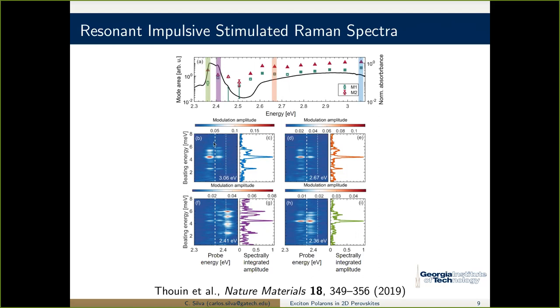So again, you saw this phase shift around exciton A. All of these normal modes, this Raman spectrum, is all centered around exciton A. You see exciton B, not much activity. We go to lower in energy, and we see basically the same thing. We're still injecting photocarriers, albeit with lower energy. But when we resonantly excite the two excitons, we see very different things. So we resonantly excite exciton A. Now we're pumping into exciton A and probing around exciton A and exciton B.